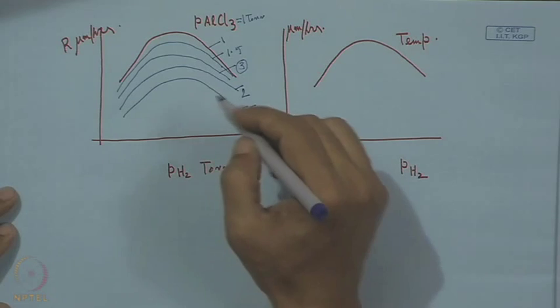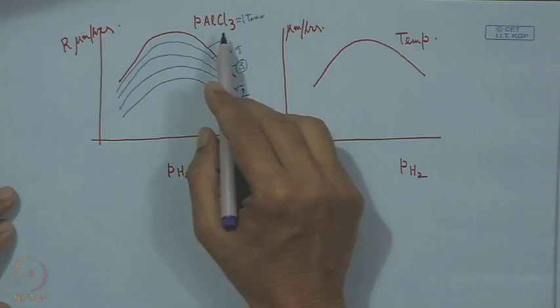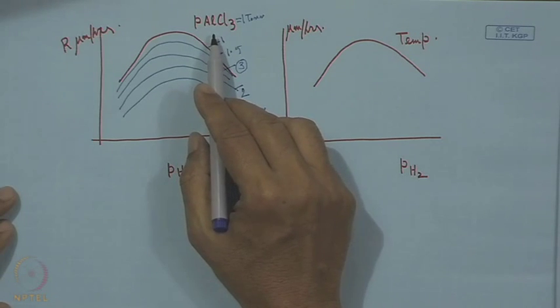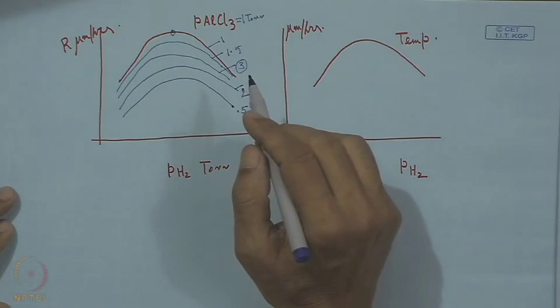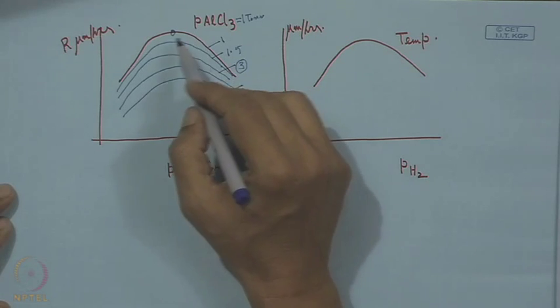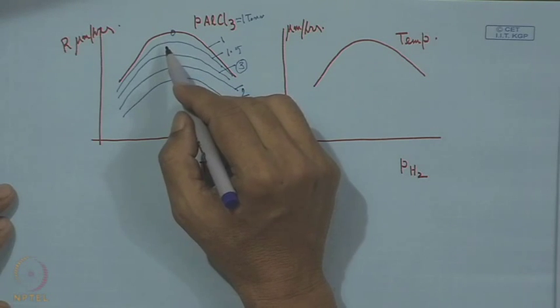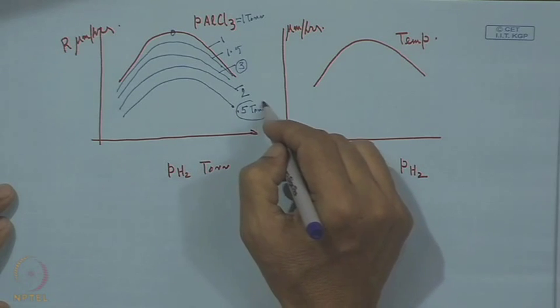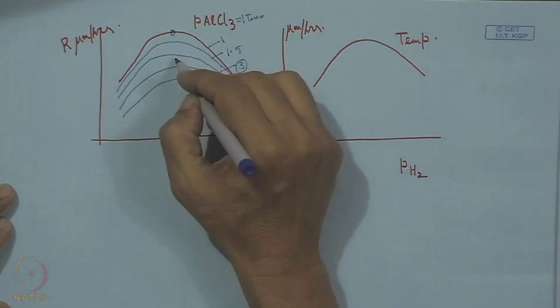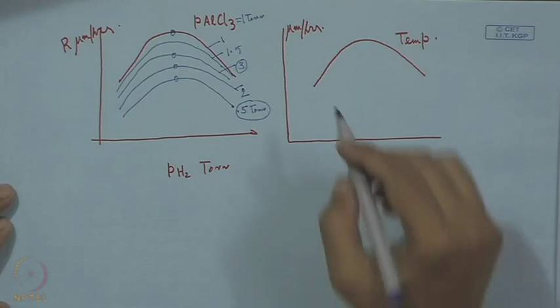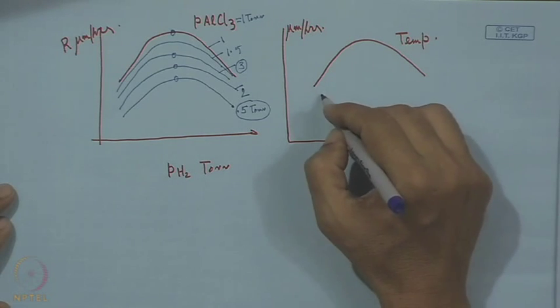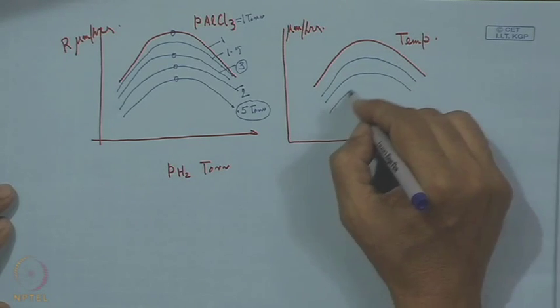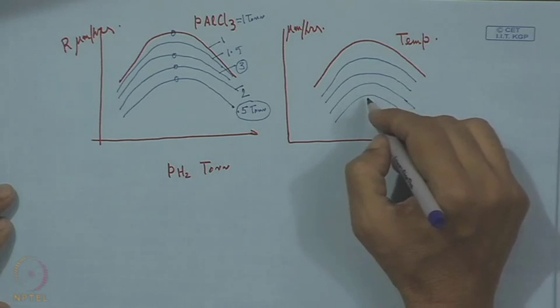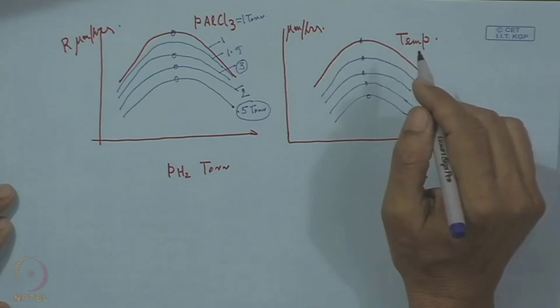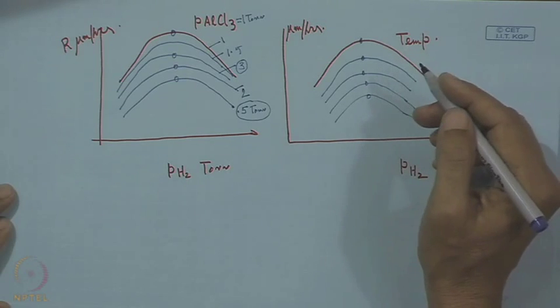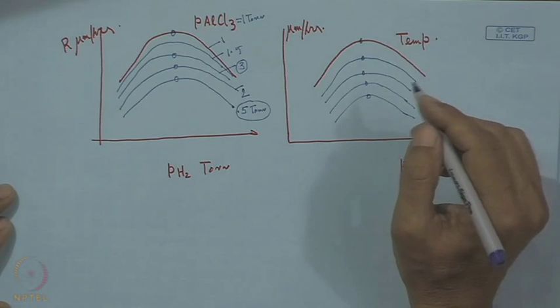That means, as we increase or decrease the partial pressure of AlCl3, definitely the peak point gets shifted, and it is also the same fact that the highest yield can be obtained at an intermediate value, and at the low end of PAlCl3 or the very high value of PAlCl3, then we have a low value of the yield. Now, for the temperature, what we see here is that with this pressure, the higher the temperature, the higher is the growth rate, and this is actually the activation, and it is a temperature dominated reaction. So naturally, the higher the temperature, the reaction rate increases, and as a result the growth rate is also increasing.